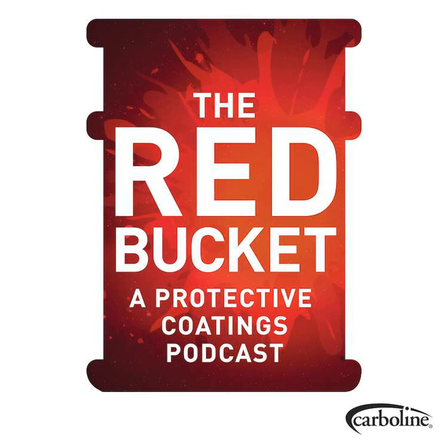And in the case of galvanizing, you actually have a gradation between zinc-iron alloy at the surface of the steel, and then all the way up to the zinc-air interface, you have close to 100% zinc. And again, it's because of that metallurgical bond, because of the galvanizing process that creates this gradation of a zinc-iron complex that ultimately, as I said, results in 100% zinc at the surface. So you have 100% zinc at the surface in galvanizing.